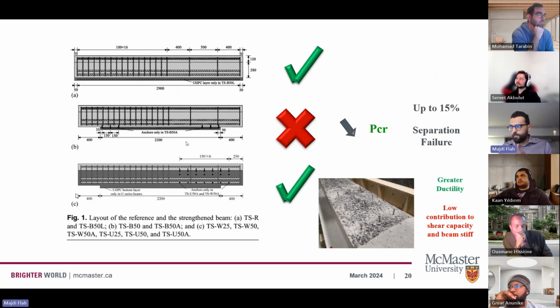However, when we put the UHPC layer at the bottom, it's not really practical to have it up to the ends or up to the supports, because let's say that you have a bridge. Under the supports, we're going to have the bearing pads. So that area is very limited. So we cannot really put our UHPC layer.